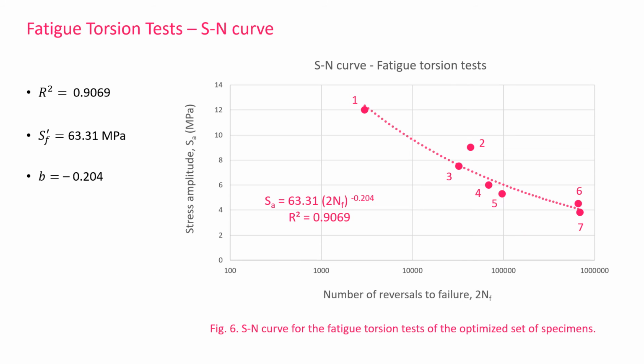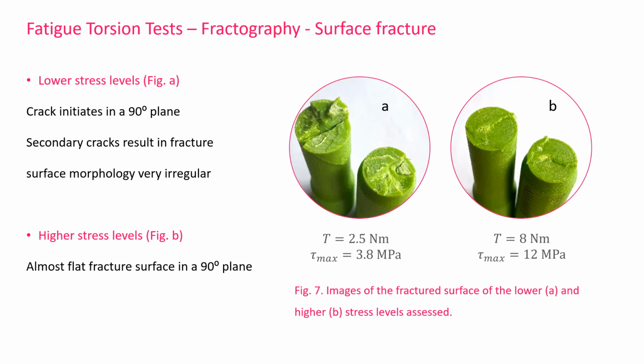From the 7 stress levels assessed in fatigue torsion tests, the S-N curve was constructed and it is shown in Figure 6 with an R² of 0.9069. From the data, it was possible to estimate that the fatigue strength coefficient is 63.31 MPa and that the fatigue strength exponent is minus 0.204. It was observed that at lower stress levels, cracks initiate in a 90-degree plane with the specimen